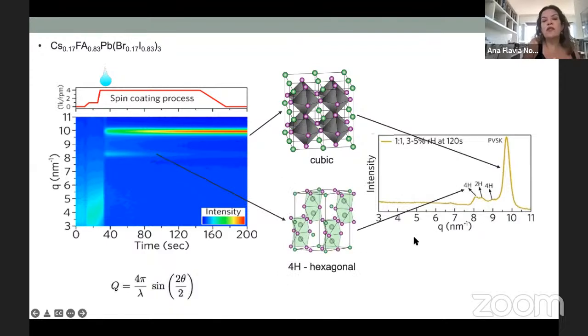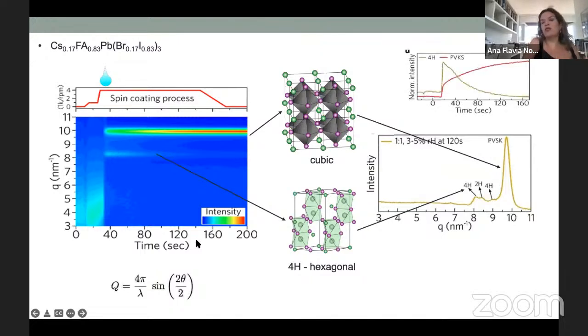Also it is interesting because as we're doing this with time, you can plot intensity versus time. And this is what you see here: first, we have the formation of the hexagonal phases. And as the solvent starts to evaporate, then you see the conversion to the cubic perovskite. So the hexagonal phases are converted to cubic perovskite with just evaporation of the solvents from the precursor solution.